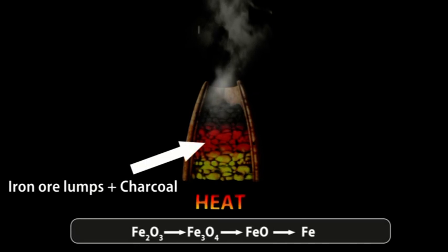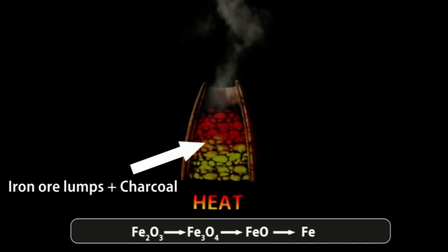As the reduction was carried out by charcoal, there was no chance, or rather little chance, of sulfur pickup in the final iron, whereas the phosphorus content was more, because all the phosphorus present in the iron ore was picked up during the process. So the final product contained less sulfur, but the phosphorus percentage was about 0.1%.